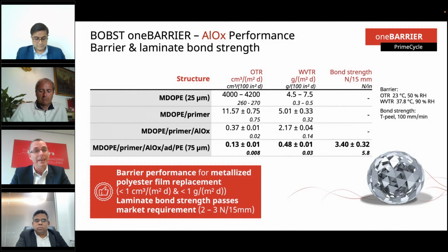We have additionally assessed the laminate bond strength of this duplex laminate, and we found an average bond strength of around 3.4 newtons per 15 millimeter. So in summary, we can conclude that with our transparent one barrier MDO-PE structure, we've obtained barrier performance equivalent to metallized polyester film, and we also satisfy the market requirement in terms of laminate bond strength. Next slide, Ben.